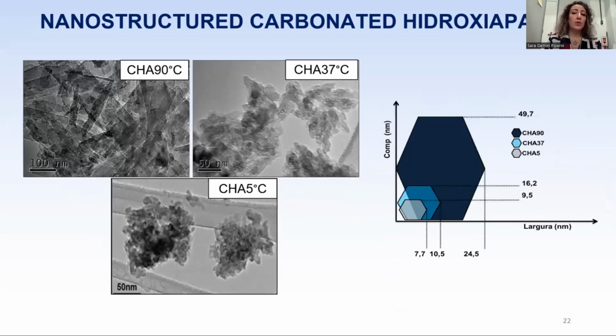Generally, we buy the hydroxyapatite that is commercially available, but this hydroxyapatite is synthesized at very high temperature. So this is different from what happens in the human body. And for this reason, we chose a different synthesis way, a wet synthesis that allows us to work at 3 different temperatures: 90 degrees, 37 degrees, and 5 degrees. And this produces a material similar to the bone tissue.